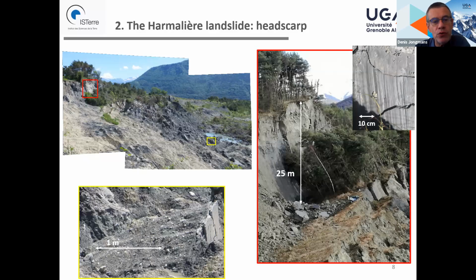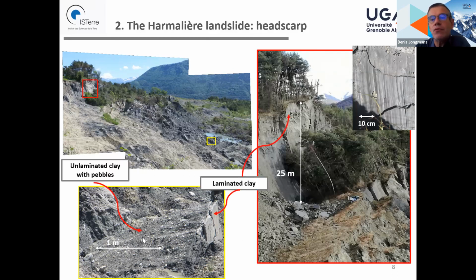An interesting point is that if we look inside the landslide, we can find these laminated clays, as you see here, but also another type of material made of unlaminated clays with pebbles. You can see the pebbles very well here. And this second material was probably generated by the glacier. We see some episodes of advance and retreat, which eroded the sediment into the lake and deposited this heterogeneous material. So we find layers of this material.